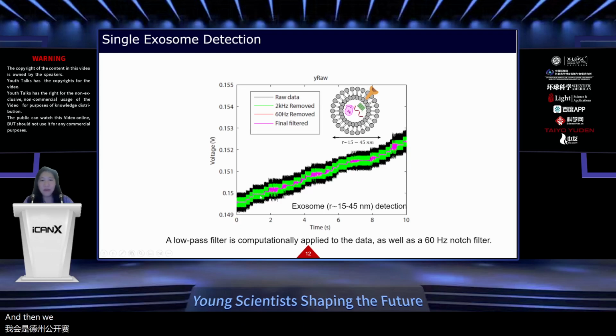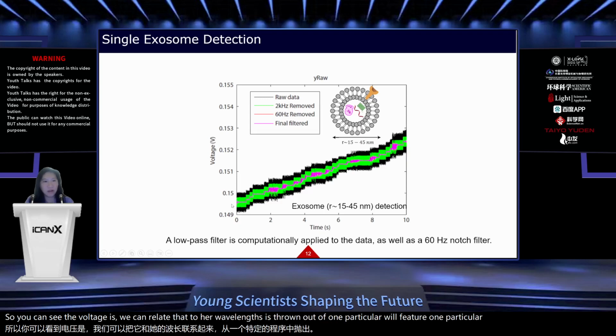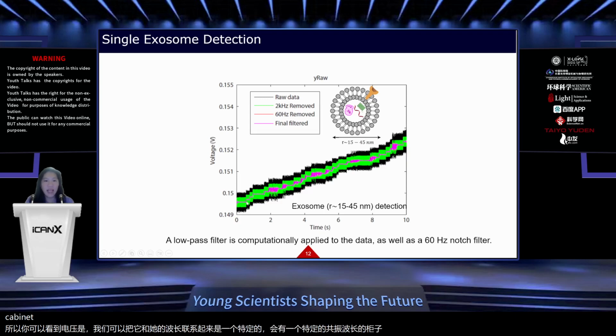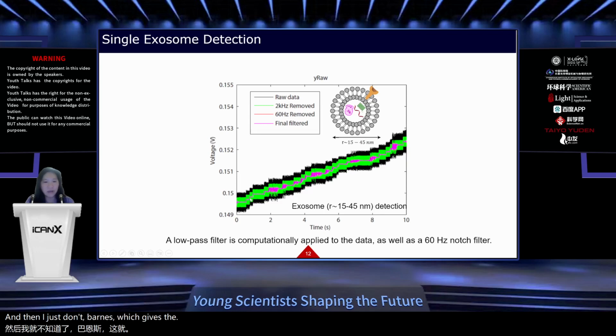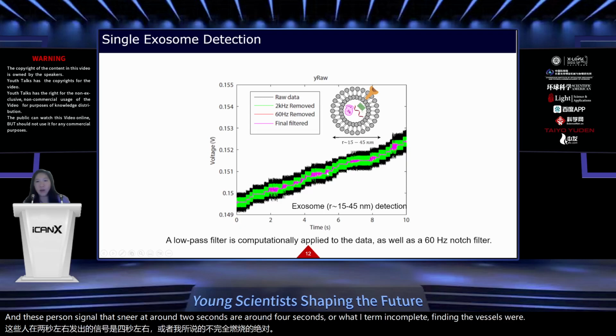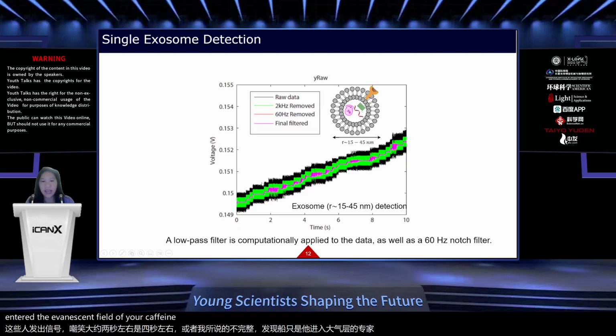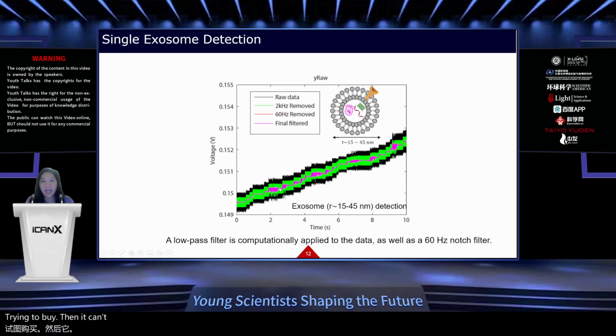And then what we do is we remove known sources of noise, and then the pink color is our final filtered data. So you can see the voltage, we can relate that to our wavelength. So you start out at one particular voltage or one particular resonance wavelength of your cavity. And then as an exosome binds, it shifts the wavelength, and so on and so forth, which creates this staircase-like graph. And these bursts of signal that you see at around 2 seconds or around 4 seconds are what I term incomplete binding events. So it's where an exosome has entered the evanescent field of your cavity, it's trying to bind, but then it can't quite bind, and then it eventually binds.